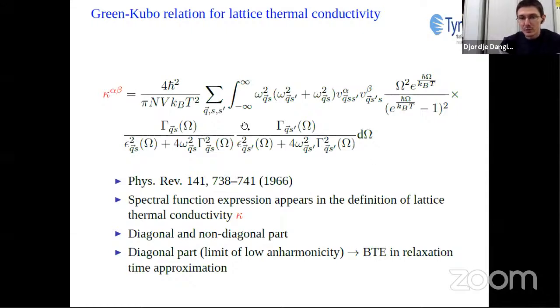Important thing to note here is that we have an integral over the frequency range. And under the integral, we can recognize the phonon spectral function. So we did include the entire information of the phonon spectral function in our calculation of the lattice thermal conductivity. Another important point to note here is that the summation goes through two branch indices, S and S'. So we can split this expression in two parts.